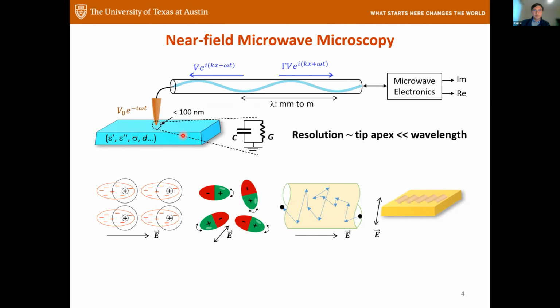So I have some movies, so let me wait a little bit. Let's start from very negative. So you see everything is insulating, and gradually as we turn on the gate, this part gets conductive and this part gets conductive later. And the imaginary part is monotonically becoming brighter and brighter. The real part, which is the lossy part, gets bright. And at some point, it starts to dim and then it disappears at a very high gate voltage. Right? So if you just plot the overall signal as a function of backgate voltage, they track the simulation curve fairly well. So I would say at least this tells us the picture is correct.